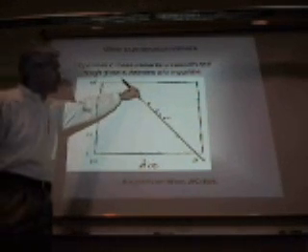When you look at the parameters you get from this, the parameters for this liquid layer again are nowhere near water-like. So this is really not just a molten water layer you see here. There is something else in this experiment. Of course, it hasn't been quantified, so I can't really say what it is. The only thing I can assume is impurities. There's nothing else which can change the parameters so much that it's so far away from anything you would expect for pure water.